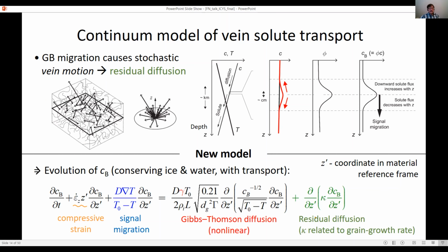And I call this the residual diffusion because even if you block the veins, so chemistry can't flow along the veins, this is going to happen. You get residual diffusion from grain boundary motion, which doesn't cease.